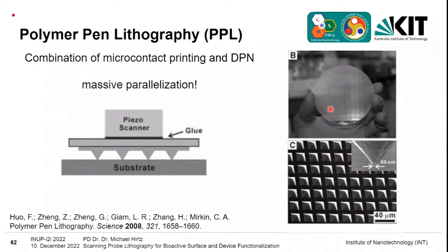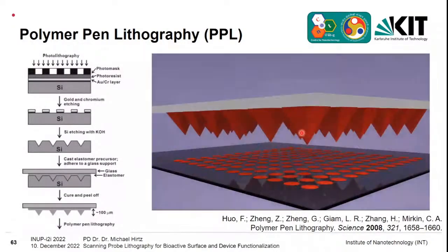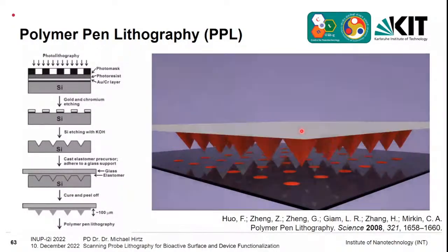You can see here a wafer-size stamp that's filled with this. With a 40 micrometer pitch, for example, you can have several tens of thousands of these structures on a square centimeter. And they all still have a fairly sharp tip, about 60 nanometers in this case. And this then allows you to print features onto the surface.